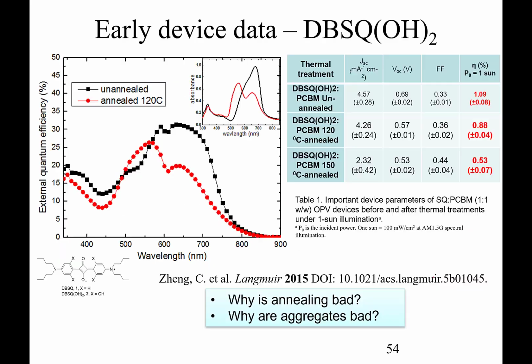There's some very early device data in here from about 6 or 7 years ago. So the efficiencies are really modest in here. We've got about 1.09 efficiency, not a lot. And this is these dibutyl squaraine materials in here, unannealed, and we thought, okay, what's going to happen? We're going to anneal these samples. When we anneal these samples, what we find is we get this broadening of the spectrum, and what we've typically found is that as we anneal, the efficiency decreases.